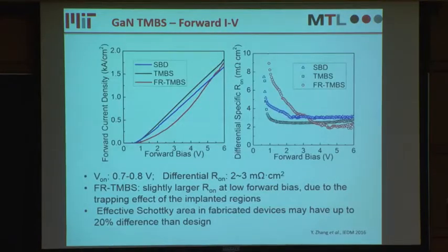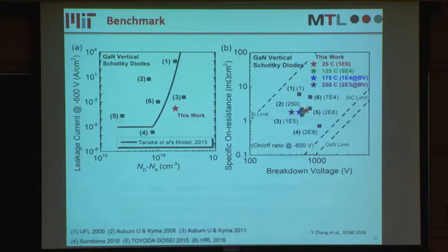Looking at the forward characteristics, all these devices have a very good turn-on voltage below 1 volt. The field ring TMBS is a little slower in turning on, because of the impact of the implanted regions. But all the devices have a quite decent on-resistance value, 2 to 3 milliohm-centimeters squared.